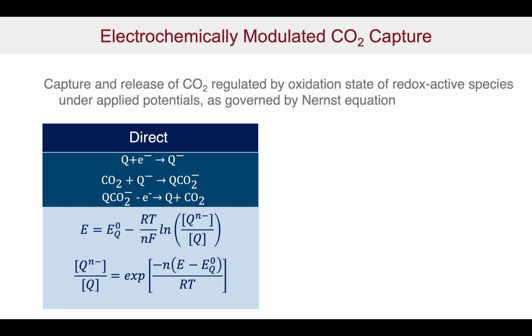There's a direct approach, which is shown here, in which you have a species that will be reduced, and then this reduced species interacts very strongly with CO2, so the CO2 binds directly to the species of interest. And then when we're fully loaded, we can reverse it and oxidize the species to give us the Q back again and the pure CO2. The actual fraction of the species that is reduced is very strongly governed by the Nernst equation, in particular by the applied potential relative to the standard state potential of the redox group. So we can regulate this by going back and forth in terms of the voltage.